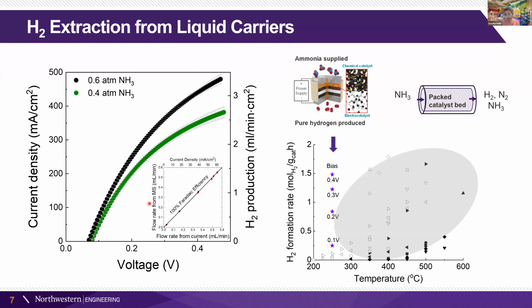And additionally, we can pump it electrochemically so that one could automatically have pressurized hydrogen, whereas again, if you use a packed catalyst bed, you have to separate it and then have another device to pump the hydrogen, which is what you normally do if you put hydrogen into a tank. You're not going to use it at 1 atmosphere. You're going to pump it up so you have some reasonable number of hydrogen molecules in your tank. So this was great. And I'll also say that we also demonstrated using our mass spectrometry that there were no nitrogen oxides being produced, so no NOx generated, which is important also from the perspective of the clean environment.